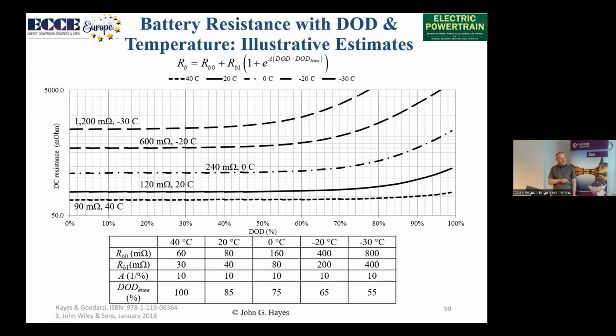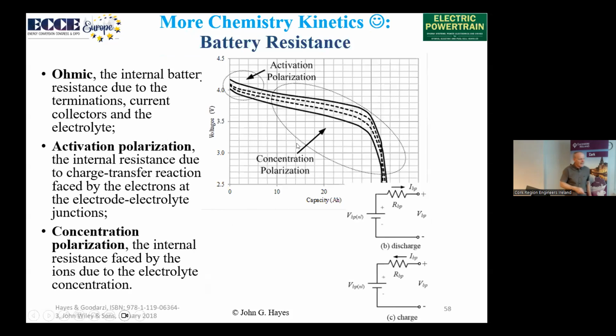But as we discharge, so here we're fully charged, depth of discharge is 0. As we discharge it, the resistance is heading up exponentially. So now if we're significantly discharged and it's extremely cold, this resistance is going to be very high. So if I go back to the problem I had here, if we're charging and this resistance is super high, to get a little bit of current in there, I'm going to get a very high voltage.